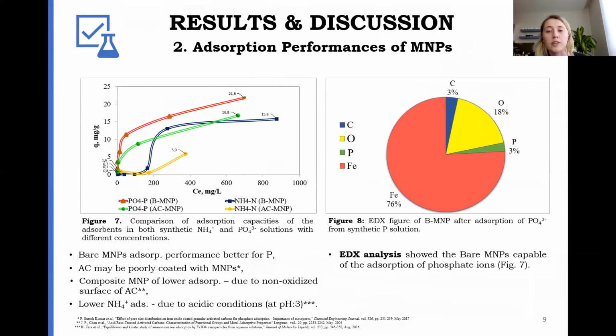The performances of the adsorbents and the amount of the adsorbed ions were demonstrated in figure 7. The phosphate adsorption on bare form resulted better. Here you see in figure 7. One of the reasons may be attributed to the activated carbon possibly being poorly coated with magnetite nanoparticles. So that's why the performance of the composite form resulted lower compared to the bare form. You can see in the figure.